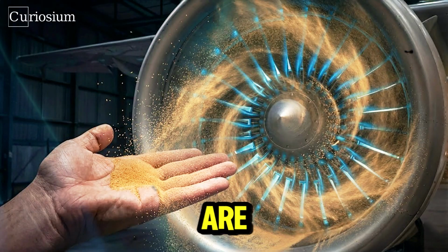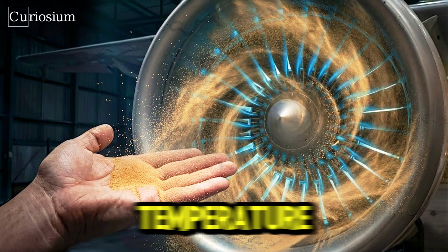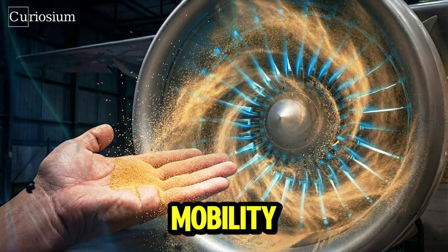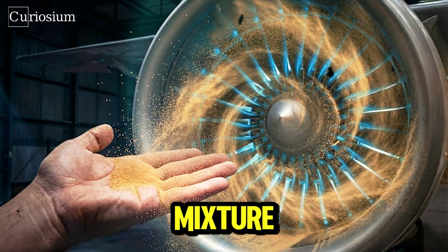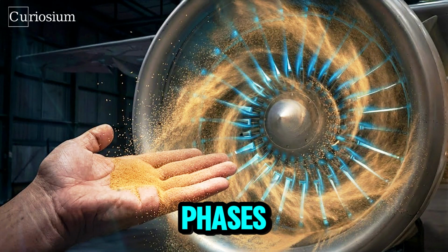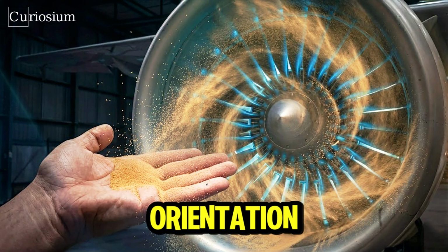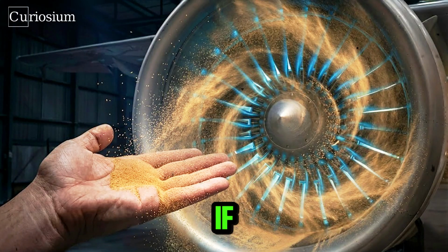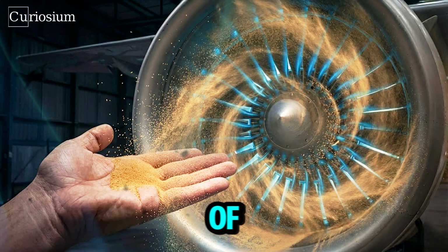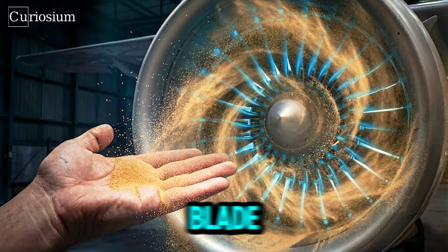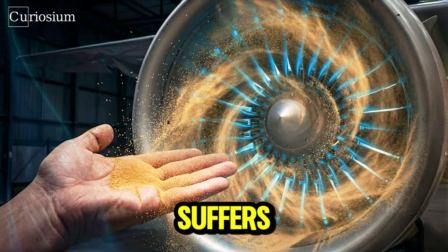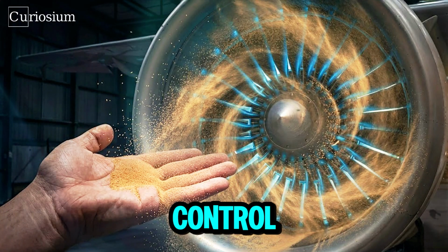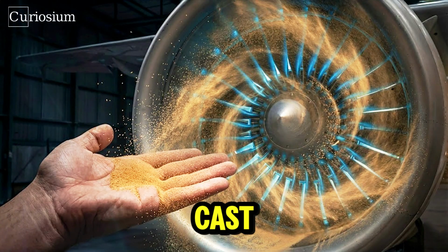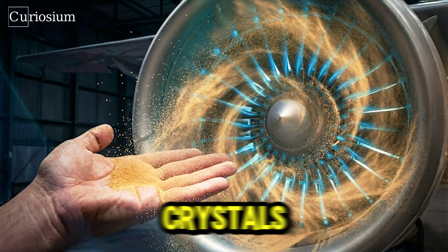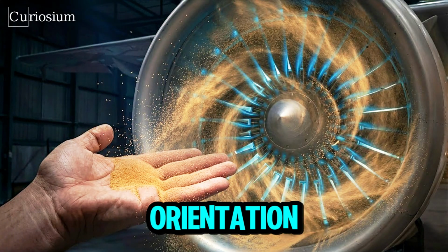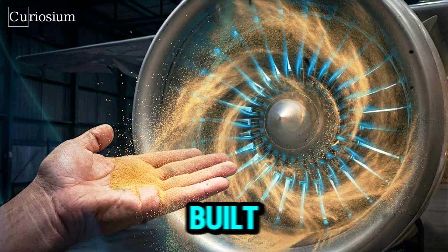After casting, the blades are heat-treated again, almost up to their melting temperature. This gives atoms enough mobility to rearrange into the ideal mixture of gamma and gamma prime phases throughout the crystal. Even the orientation of the crystal matters. If the lattice is tilted too far away from the direction of the main load, the stresses inside the blade change, and performance suffers. With modern process control, manufacturers can successfully cast the vast majority of blades as single crystals with the correct orientation. Let us stop and recap what we have built so far.